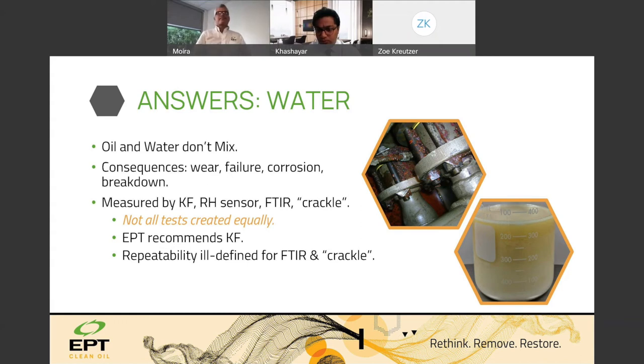Crackle test. We don't see much of this anymore, but in, say, heavy machinery or in the manufacturing industry, the crackle test is really great because you can do it on site and you just drop one drop of oil onto a griddle. And that hot plate, if it bounces, you know that there's water in it, right? So a high level of water in it. So this is not normally effective anymore in critical machines.